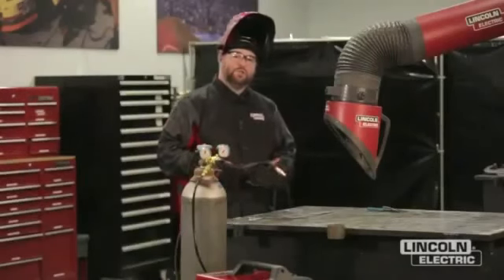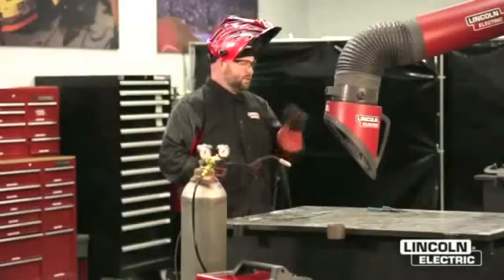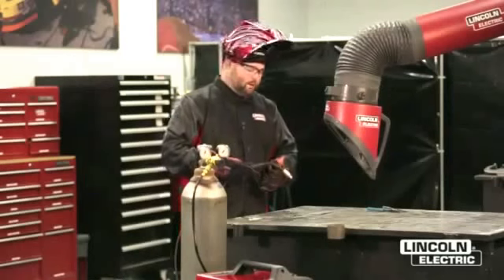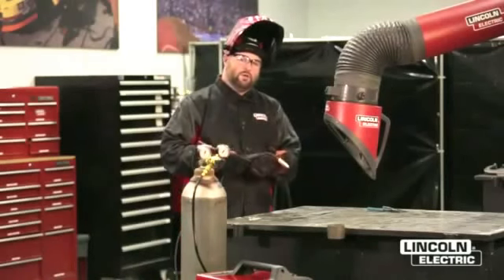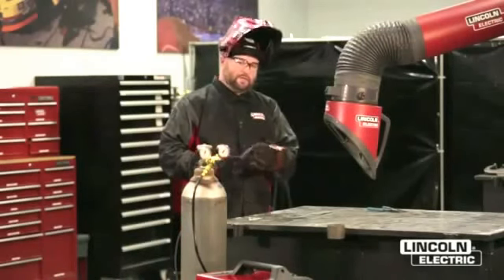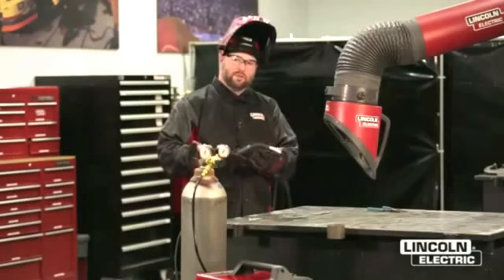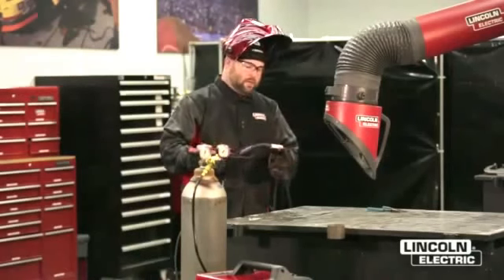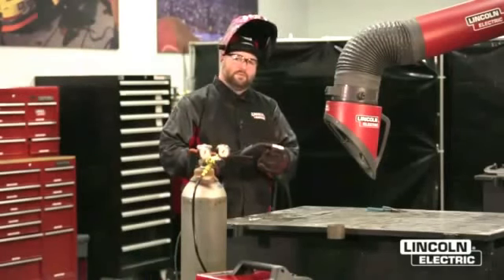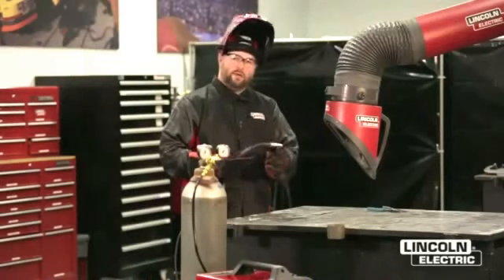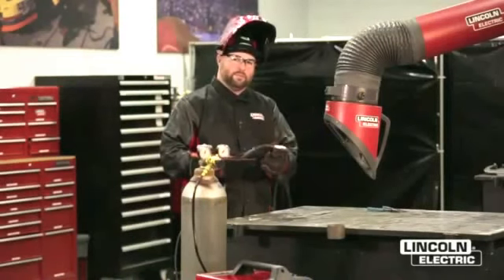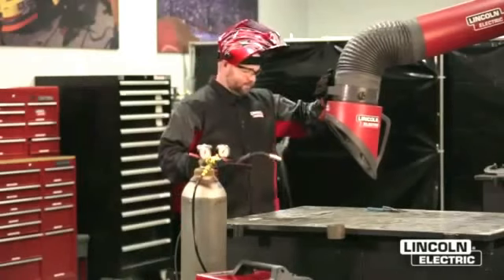Now we're going to look at too short of a contact tip to work distance. We're going to go ahead and make a weld, and you're going to notice that I'm too close to the plate, and a couple things could happen. One is my nozzle could drag in the weld behind me. The other one is that my contact tip to work distance is so short that it'll actually burn back up into the tip. So let's make a weld and see what happens.